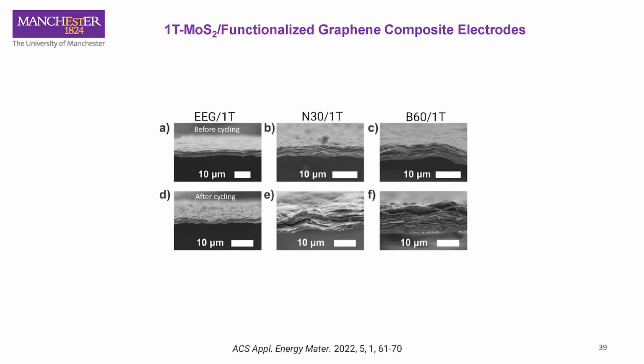Also with cycle life, the graphene by itself, after cycling, the structure remains basically the same. These functionalized materials, you can see, have a much higher available surface area. You're basically preventing these layers from restacking and collapsing in on each other. Higher available surface area gives you much better performance.